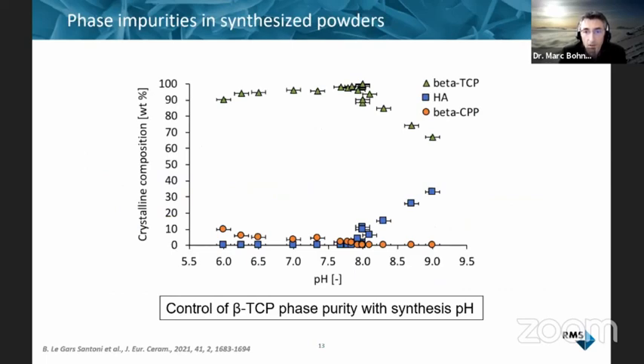And so how can you control the phase composition? Simply by changing the pH. Bastien did a lot of experiments and varied the pH from 6 to 9. If you have a low pH, you form the pyrophosphate, so the beta-calcium pyrophosphate. If you have a high pH, you form hydroxyapatite. And the pH of 8 seems to be ideal in terms of purity.